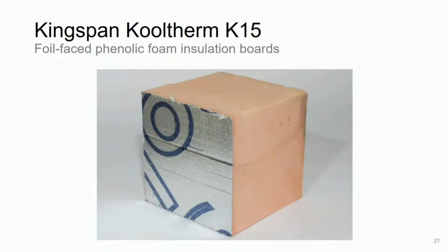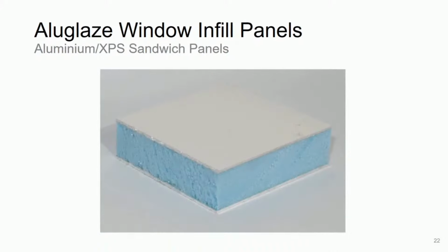Kingspan Kooltherm K15 insulation board, shown here. I will refer to this simply as K15 as I go forward. This product consists of a phenolic polymer foam core, faced on both sides with a thin aluminium foil, which again is only a fraction of a millimeter thick. The aluminium foil facer in this case has small perforations in it, which if you look very closely at this picture, you can see as small dots on the foil's surface. And finally, Aluglaze window infill panels, shown here. And this product consists of 2 flat aluminium sheets, each 1.5 millimeters thick, with an extruded polystyrene, or XPS, polymer foam core, which is 25 millimeters thick.